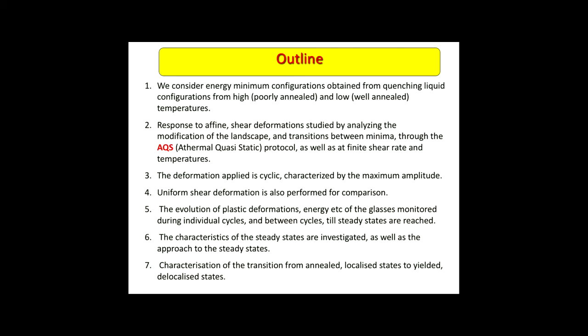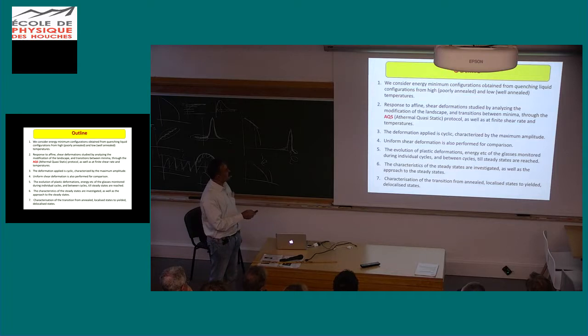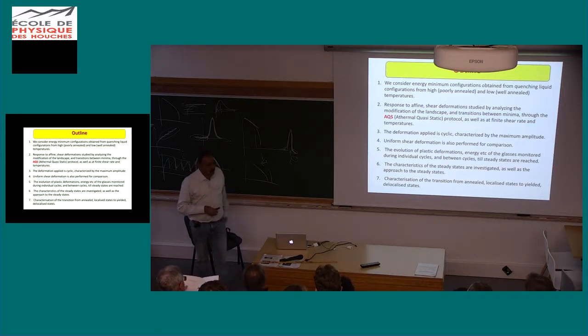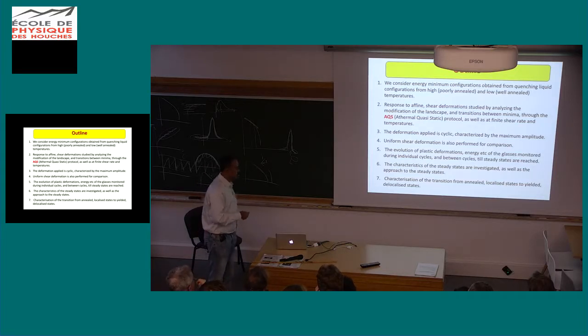Okay, so here's the outline of what we do. We consider energy minimum configurations, which we call glasses, obtained from quenching liquid configurations from high and low temperatures, and when it's quenched from high temperatures, we call them poorly annealed glasses. When they're quenched from low temperature liquids, we call them well annealed glasses. This is a way of assessing the importance of the initial conditions, and by and large, for what I'm going to talk about, initial conditions are not going to be too significantly important when we study cyclic deformation.